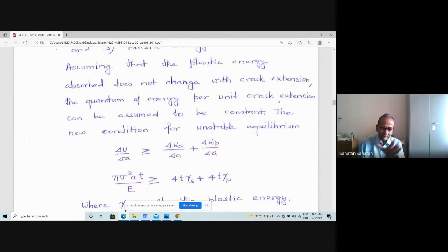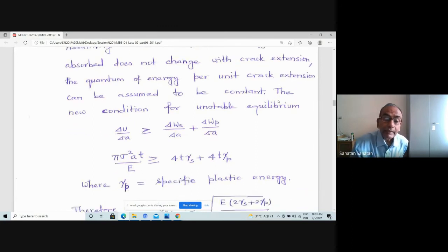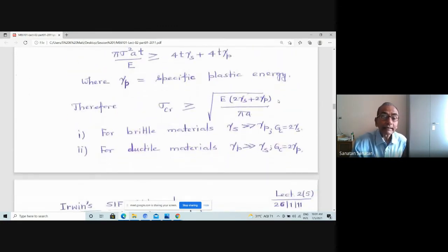So therefore, you see that the earlier equation was pi sigma squared a T by E greater than or equal to 4T gamma S. But now they amended that there should be also plastic energy per unit crack extension. This is 4T multiplied by gamma P, the plastic energy per unit crack extension. So that's how this amendment was given. And in fact, the new damage tolerance relationship is this: sigma critical is equal to square root of E times (2 gamma S plus 2 gamma P) divided by pi times a. So, in the earlier one, this gamma P was not there. Now this gamma P has come up, and that is the amendment.